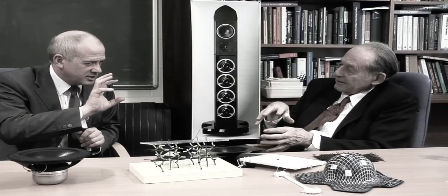And so these atoms are attaching themselves to the carbon in a helix? Yes, they go around in a helix. And that means the whole thing is regular and it can crystallize. Right. And that's important because you want crystallinity to give you a high melting point, all these sort of things. Stiffness. Yes, and stiffness. But the polypropylene is of intermediate stiffness. It's not as stiff as the polyethylene, but it's intermediate. But it suits your purposes very well, really. From the damping perspective, yes, it suits your purposes very well.